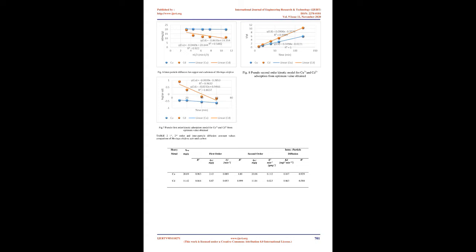B. Equilibrium studies. The equilibrium curve of copper and cadmium for the Moringa oleifera activated carbon was studied and shown in Figure 3. The copper curve shows a concave downward shape due to high affinity between adsorbate and activated carbon. The contaminant metals were in cationic form. The adsorption mechanism could occur by ion exchange or electrostatic forces due to the oxygen-containing group, COOH, on the surface of adsorbents. So, with increasing oxygen-containing groups on the adsorbents, the quantity of adsorbate also increased.